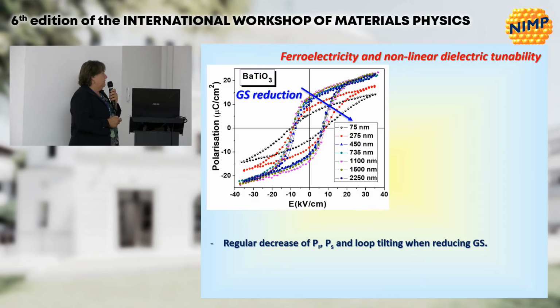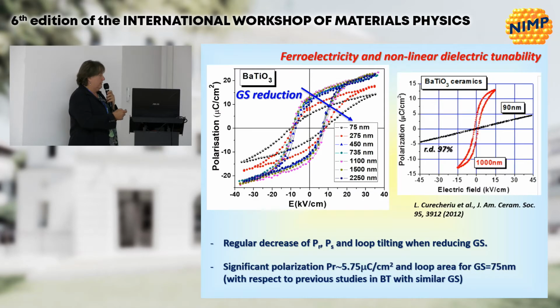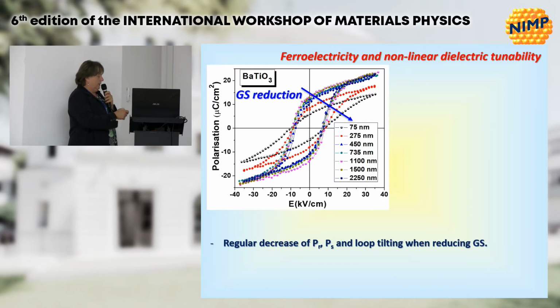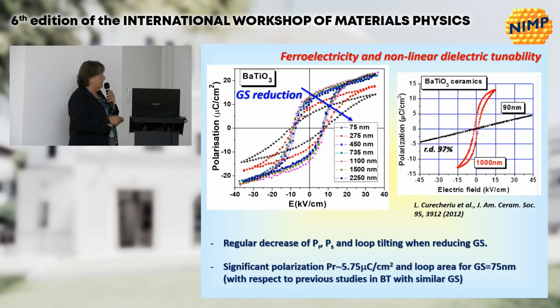This is a ferroelectricity decay that is known in many systems, and our ceramics also show the same trend. What was strange for us at the moment of investigation was that while before even dense ceramics obtained by spark plasma sintering didn't show any hysteresis loop, these ones that have a multi-phase show a loop even at 75 nanometer grain size. And this was the same for other samples that we have prepared in this set, which shows us the fact that these are somehow different, and most probably the origin is the existence of the orthorhombic state that is giving us 12 positions for the polarization reversal.